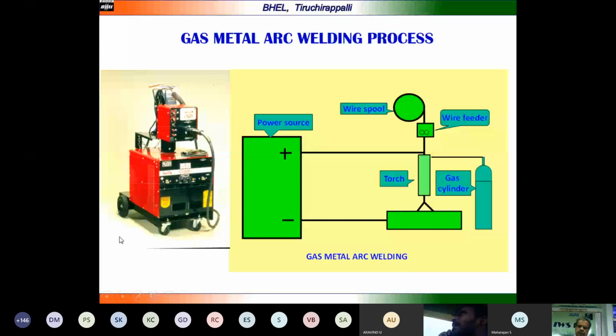The wire is fed as a continuous wire through a wire feeder and rollers, and it goes to the welding gun or torch, and the arc is struck. Here there are all the parameters, the flow meter and the pressure gauge. The advantage here is that it is a consumable electrode. Unlike TIG welding, the arc is struck between the consumable electrode and the job. Because of that, any increase or decrease in current will affect the deposition rate. In TIG welding, a change in current does not affect the deposition rate; it only affects the amount of heat given to the job.